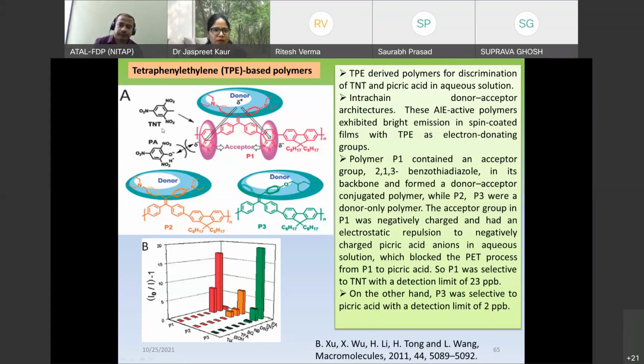Why will it not interact with the picric acid? Because in this particular polymer P1 we have 2,1,3-benzothiadiazole in the backbone. Here there will be repulsion between the acceptor and the negative charge present on the TNP. The negative charge on TNP results in electrostatic repulsion, and therefore it will not detect the picric acid. Whereas if you look at P2 and P3, they are donor only molecules. So they will not show repulsion for the picric acid molecules. They will interact with the picric acid.